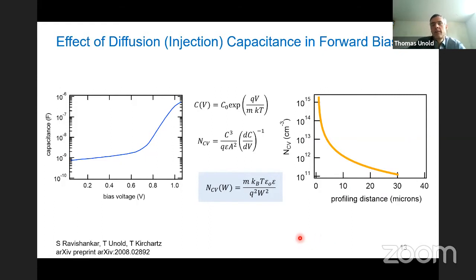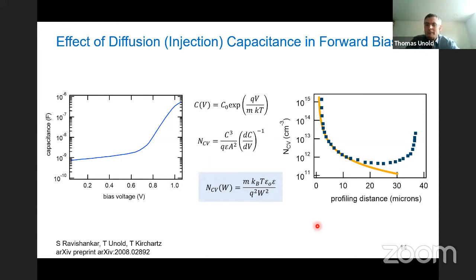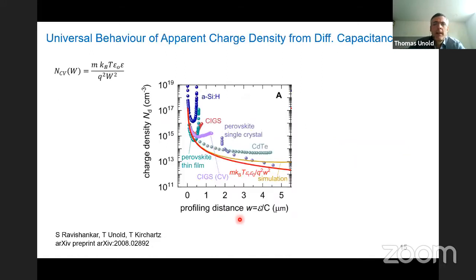Now you may remember from what I showed you before, but I plotted in here. So this is the experiment from the Science paper. You can see that this actually perfectly follows this expected shape up to 15 micrometers distance or so. And so I thought this looked very convincing. You can do this for all the data in the paper, but also I did remember I've done capacitance voltage profiling for many, many years and seen a lot of data. And I remember that a lot of these data look like this.